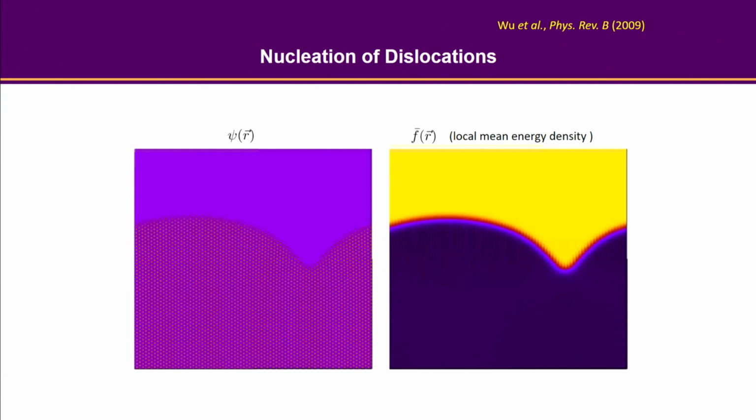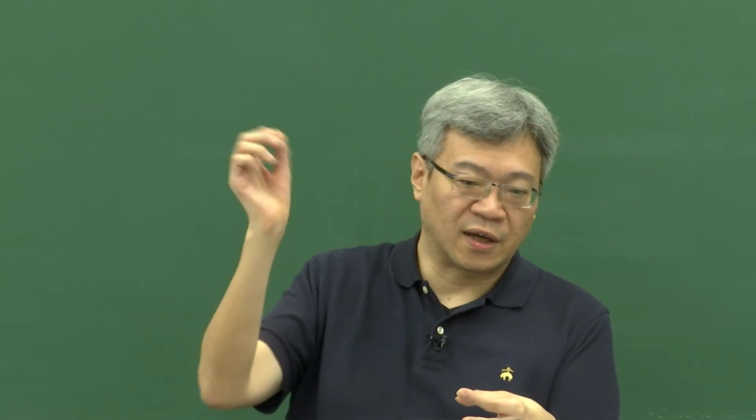So instead, something you can further do is to calculate the local free energy density. But as you know, if I just plot not the mean density but the local energy density, you are going to see also an oscillatory profile. So you have to do some proper average over one unit cell. There are several ways you can do that. You can use this FIR filter. But I think back then, the way I did this was to pinpoint the atomic positions and just take a certain position.